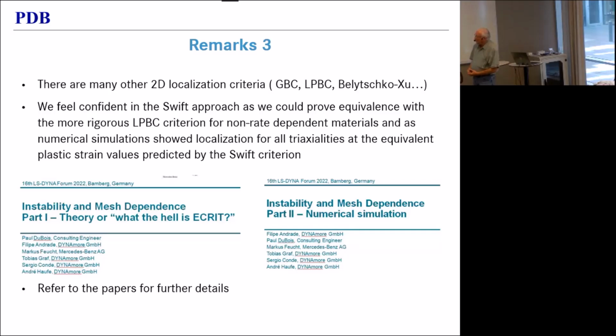You can't really test it experimentally, but you can test it numerically. Numerically, you can build test cases where you take a plate of finite elements and you subject it to loads with any triaxiality. And you can check when localization starts. Well, we've done that for, I think, 100 data points. And the start of localization was always spot on the Swift prediction. So it works out amazingly good. And if you want to know more of that, we've published 2 papers on that, which were presented in Bamberg in 2022. They're on the internet, so you can easily download them.